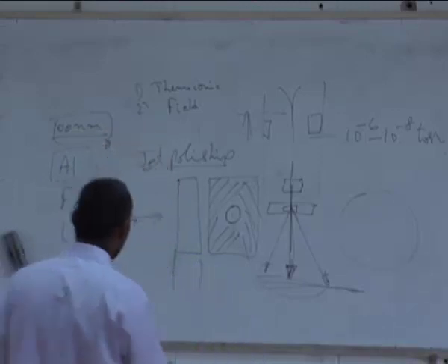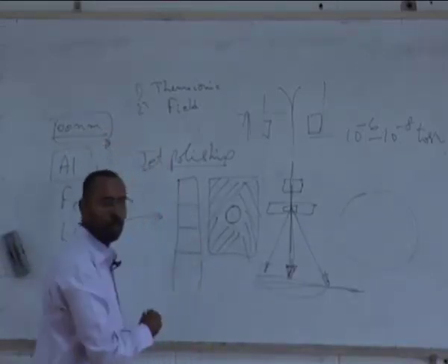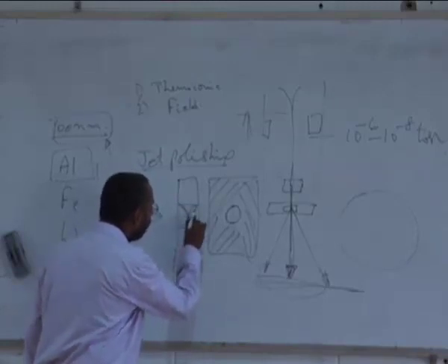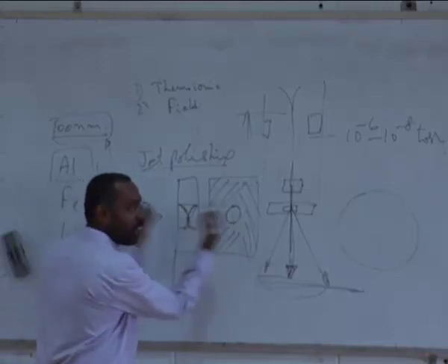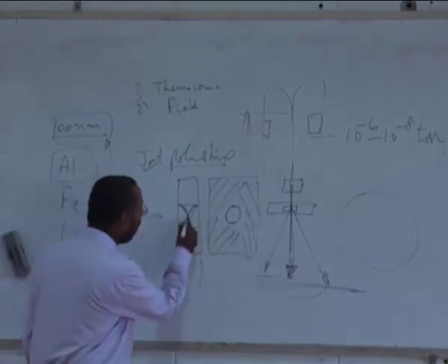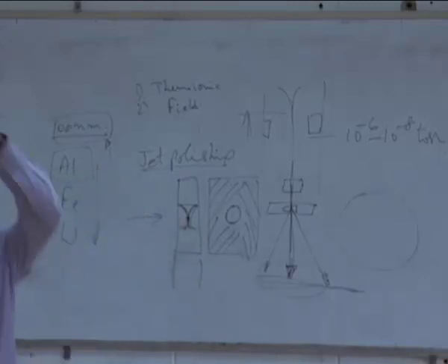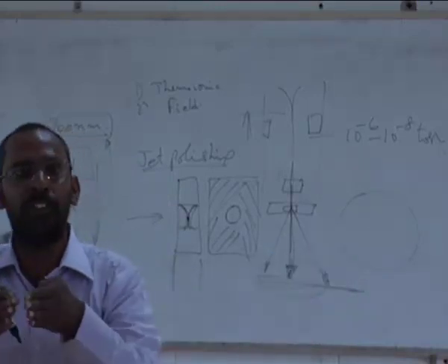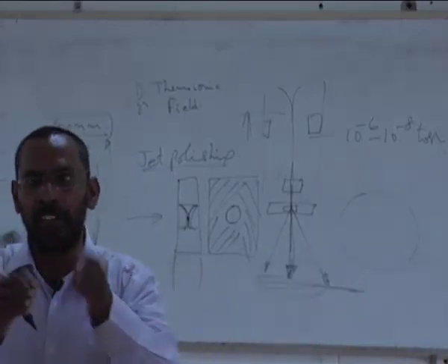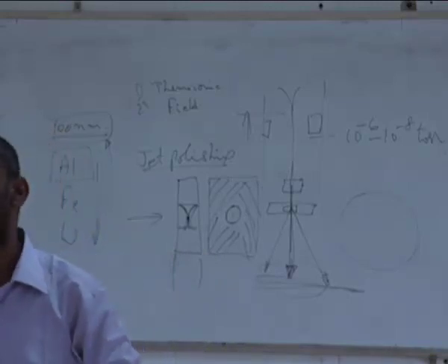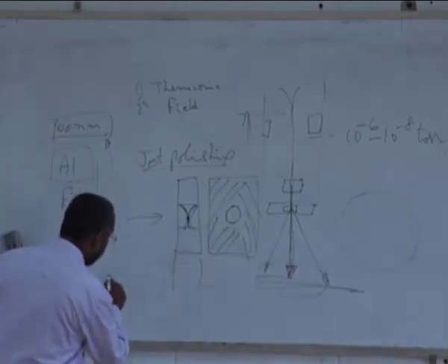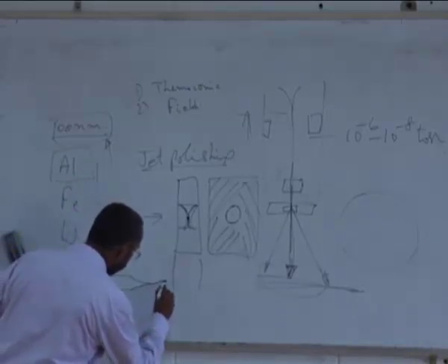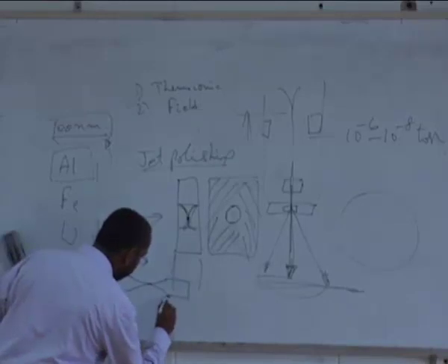When it starts dissolving, let's say it is this region which is exposed, and it dissolves slowly. At some stage, when you hold it vertically in that liquid, you will see that the dissolution starts happening from both sides. As the dissolution progresses, at the center a small hole is formed. If you look at that region where the hole has formed, it is almost like your tensile sample.